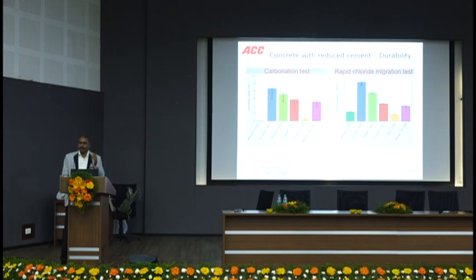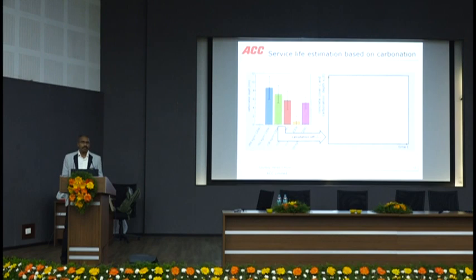So I have come across one engineer there in Goa. He is actually a chief engineer in Goa PWD. He is very stubborn on carbonation. In the construction of two famous bridges happening there in Goa, they are not allowing anything other than OPC just because the traffic level is too much there. And just because of that, they don't want to use any blended cement because it increases the carbonation depth. Then I had to give a lot of references from literature. Finally, he was convinced to go for a concrete with more than 40% slag.